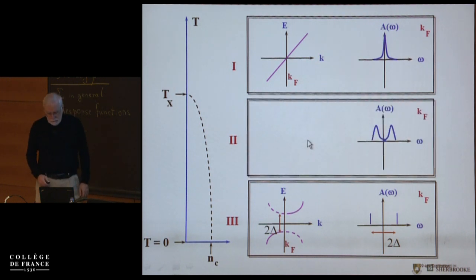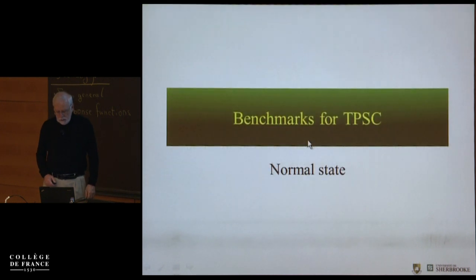Yes, Catherine? Maybe also a question for Henri. Is the normal state resistivity linear in temperature in electron doped cuprates or not? In the electron doped, it eventually goes to T square, but at high temperature, there's some linear before it saturates. I showed the resistivity curve in the first talk. I can show you later. The linear regime is in a regime where the resistivity is larger than the Mott-Ioffe-Regel value? No, smaller.